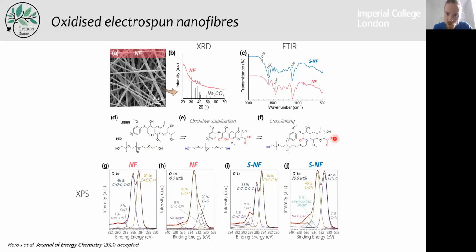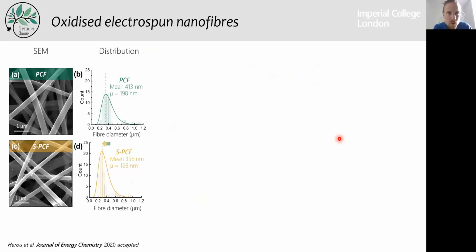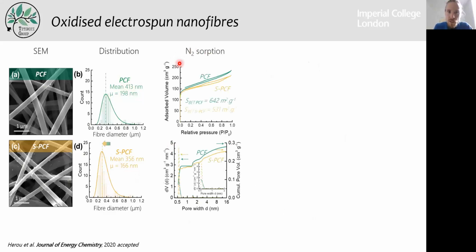And this is a scheme that shows the oxidation of lignin, which has also been shown by some peers in the literature. If we look at the non-stabilized mat, here we have nanofibers of 400 nanometers. The stabilized mat shows a slightly smaller diameter because, since it has higher oxygen content, you also have higher mass loss and lower yield, which decreases the diameter. If we look at the surface area, we have approximately the same surface area.